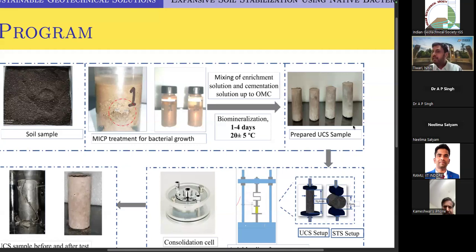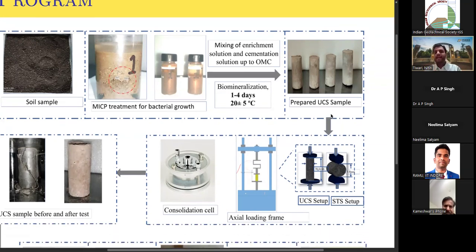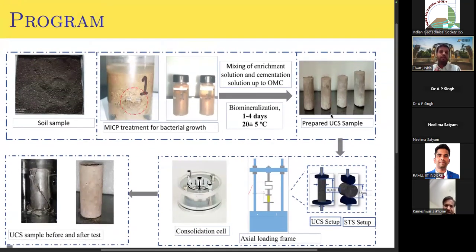And then we prepare the UCS samples, compacting the way we do the compaction, and you can see these kinds of samples appeared. And once it is done, the treatment process is done. So we do it for 1 day, 2 days, 3 days, and 4 days. In the way we do cement treatment, it is 7 days, 28 days curing and everything. For the biomineralization, 4 days are enough.